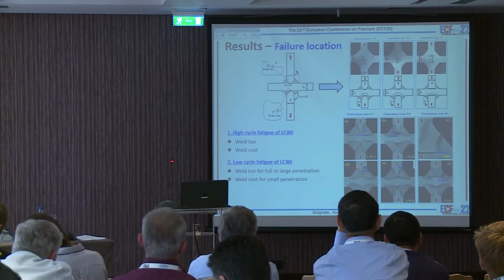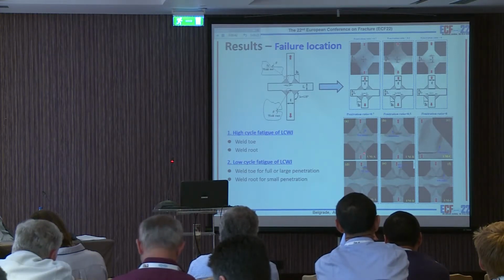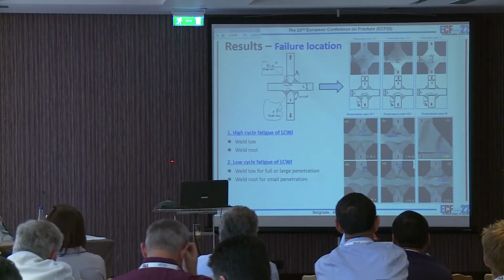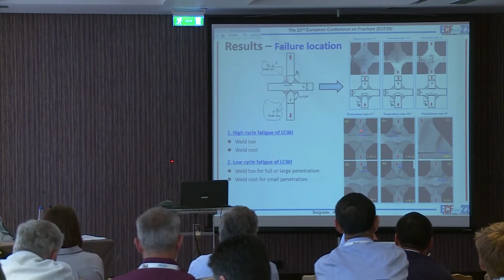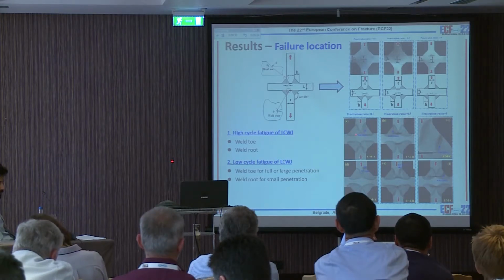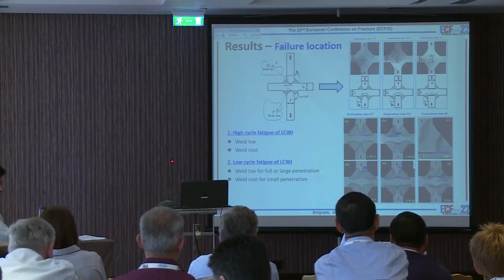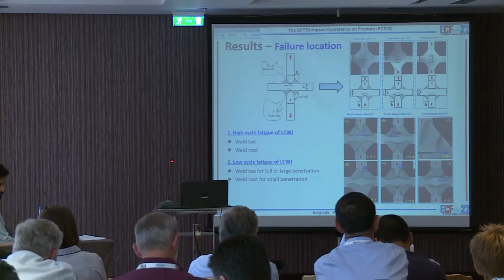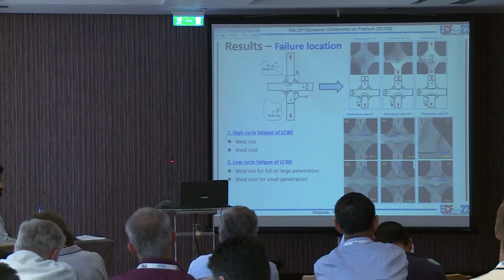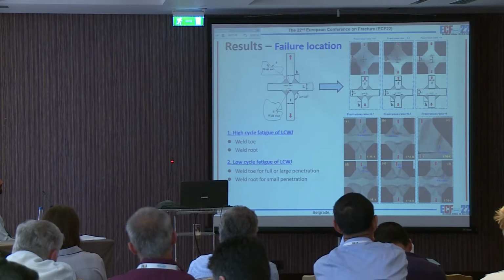So we can see for the undermatched cruciform joint, even if it has the short crack in the welded joint, the crack occurs from the welded toe, and then when the crack increased, it's a failure from the welded root.